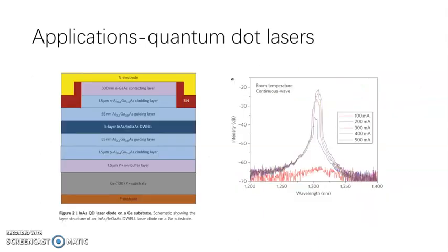And now the quantum dot lasers. The germanium layer reduces the amount of dislocations between the layers and the substrate and therefore reduces the threshold of the laser. As we can see, the lasing mode occurs when the drive current is above 100 milliamperes, at around 1300 nanometers.